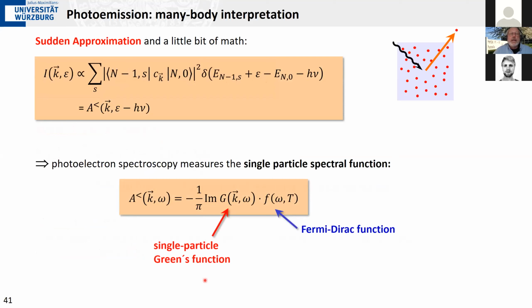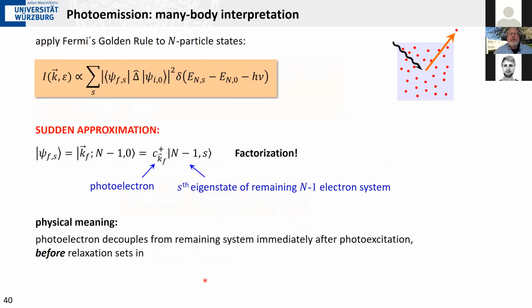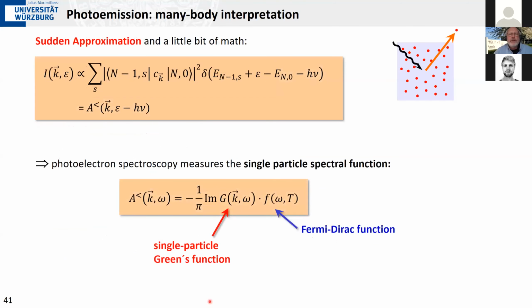And if you assume this and you plug this into this Fermi golden rule expression and you do a little bit of algebra, which takes a few steps that are non-trivial, you come up with this expression here, where you have a matrix element between the ground state. You destroy an electron with momentum k in the ground state, and then you map this onto the S eigenstate of the n-1 particle system. With some energy conservation again, and now the final state energy is decomposed into the kinetic energy of our photoelectron and the energy of the remaining n-1 state.